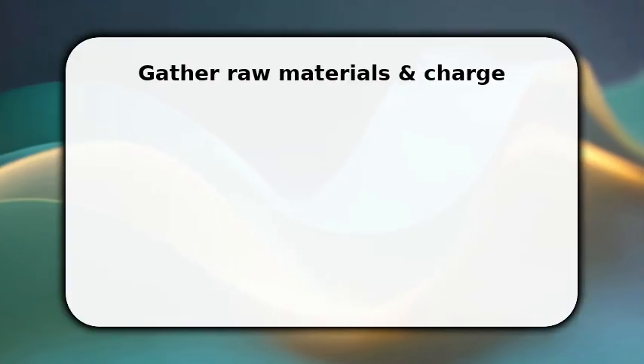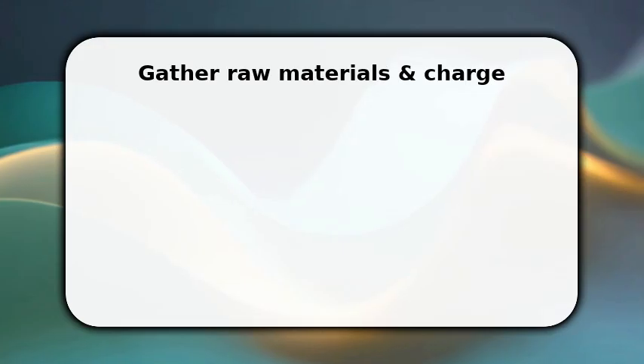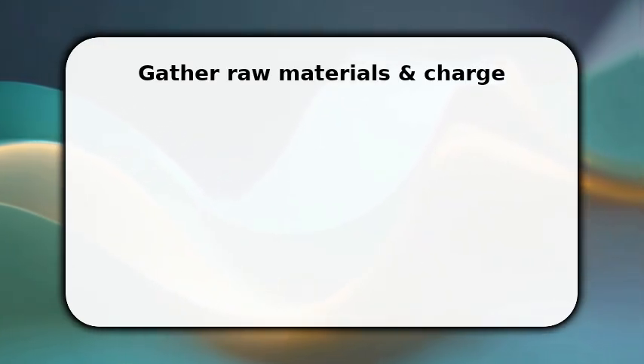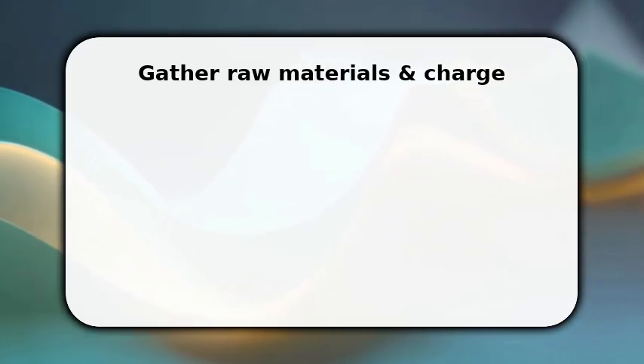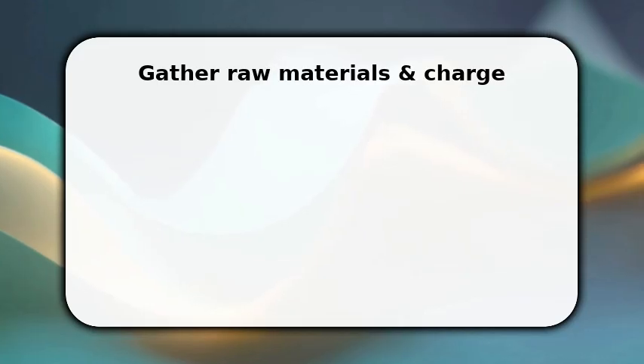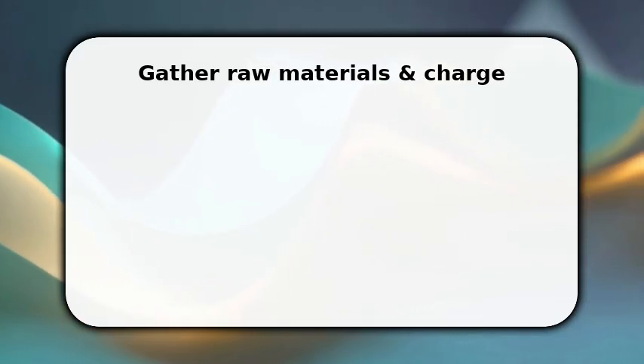You start by charging the furnace with measured iron scrap and recycled stainless, then add precise chromium and nickel to target the alloy. Once the charge is in, strike the electric arc and raise temperature quickly. The arc melts the metal and burns off contaminants.